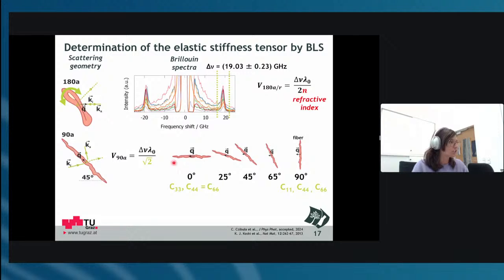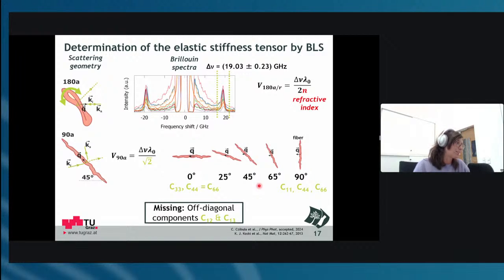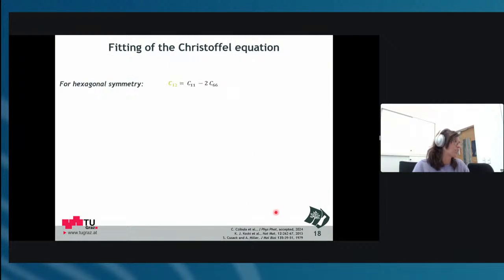So those are the measurements that I did, at 0, and then a few points in between up to 90 degrees. The angles in between are needed because, if you remember, we have the diagonal of the stiffness tensor, but we also have off-diagonal components, C12 and C13, and we need to determine them as well to have the full stiffness tensor. C12 is rather simple. It comes from symmetry: C12 is related to C11 and C66. That is a nice formula.